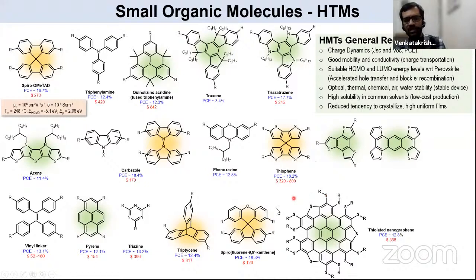Various hole transporting materials are reported in the literature, and the key ones are the three-dimensional ones that are shown in the yellow color here. And you also have the two-dimensional planar highly conjugated materials being used as hole transporting materials. I want to bring your attention to this particular structure, which is spiro-OMe-TAD, where the structure encompasses two pi planes that are orthogonal to each other. When they are orthogonal in geometry, then the pi stacking between the neighboring molecules is somehow prevented, and the peripheral R denotes here the diaryl amino groups. So the peripheral diaryl amino groups would keep the molecules far away and hence thwart crystallization actually. That's one of the reasons why such kind of molecules are close to amorphous, or they are beautifully amorphous in character. As you can see from this slide, these three-dimensional molecules, which are spiro in configuration, have power conversion efficiencies beyond 15% values.